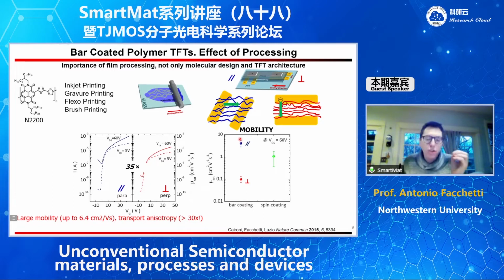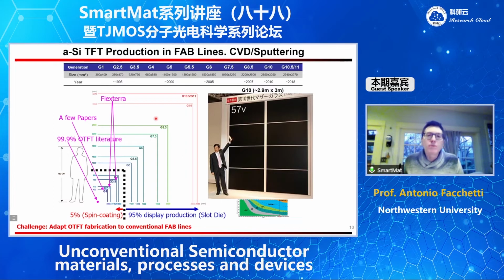So the message I want you to convey is we can do chemistry and we can do process and we can change the performance considerably. And this is very good for organic transistors. But in reality, the competitor in terms of technology is amorphous silicon, okay? Amorphous silicon has a field effect mobility of around 0.5 centimeters squared per volt second. And I showed you mobility going from 0.2 to 6.